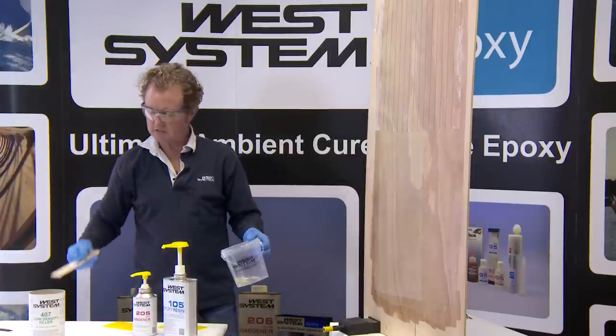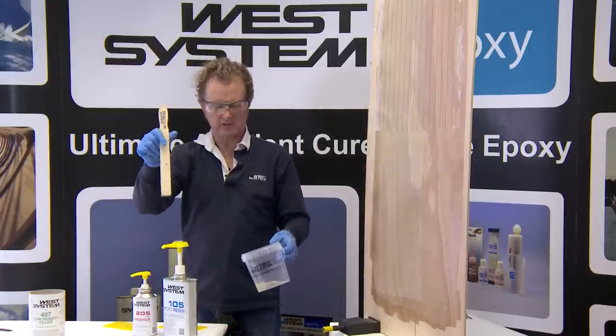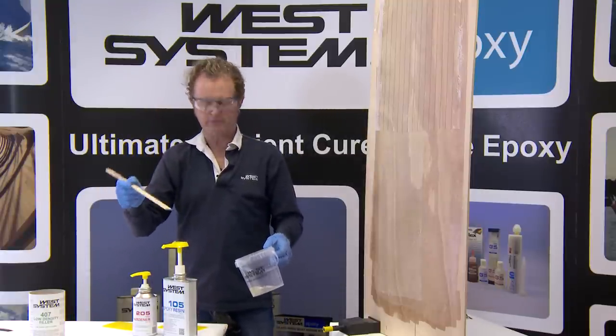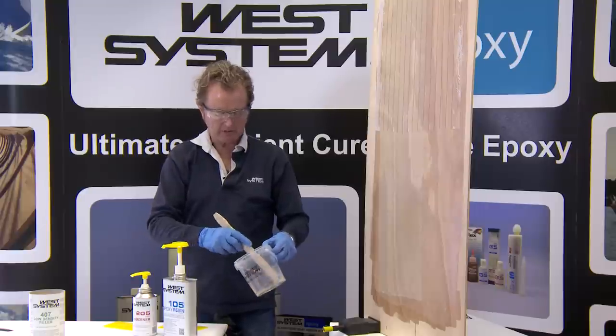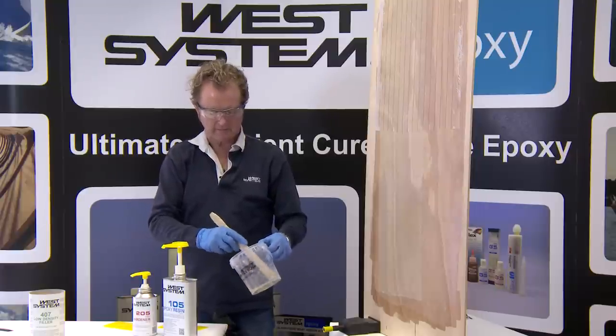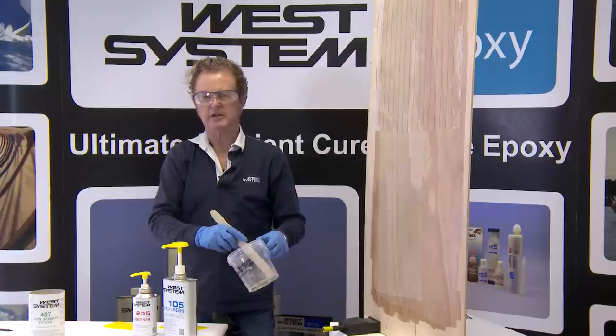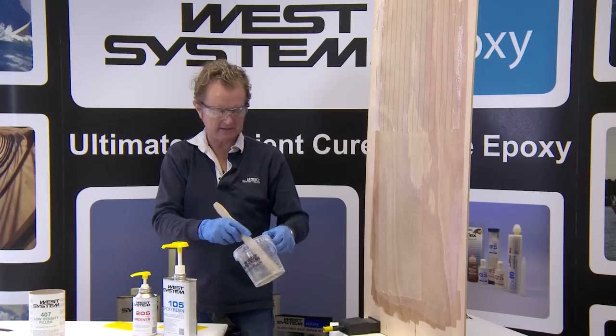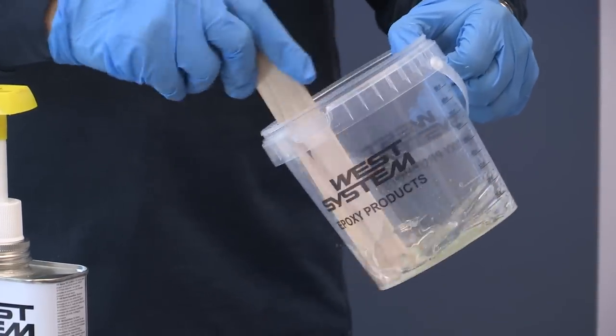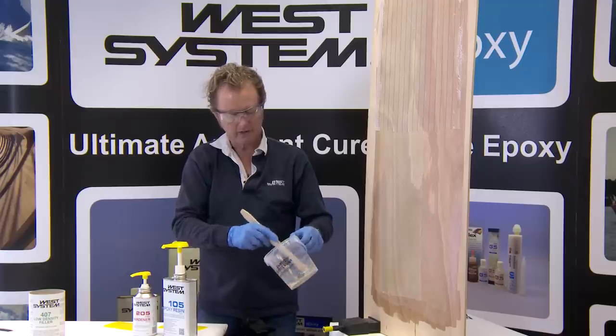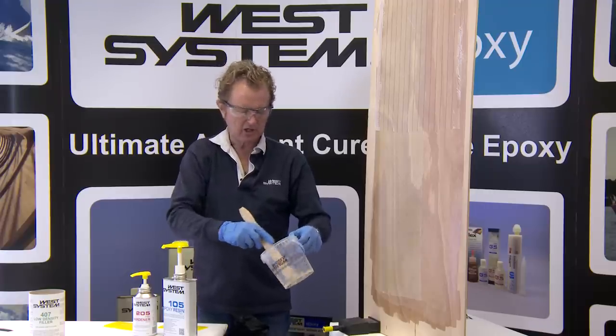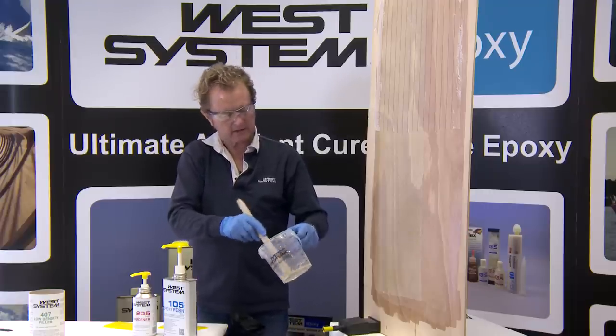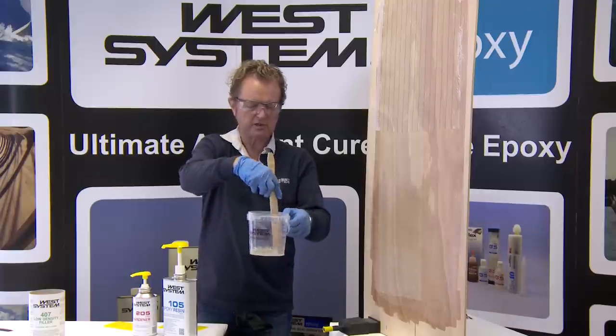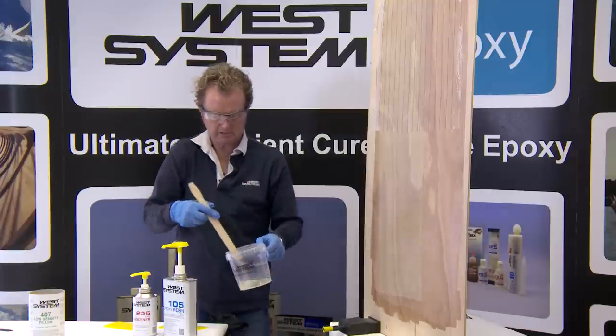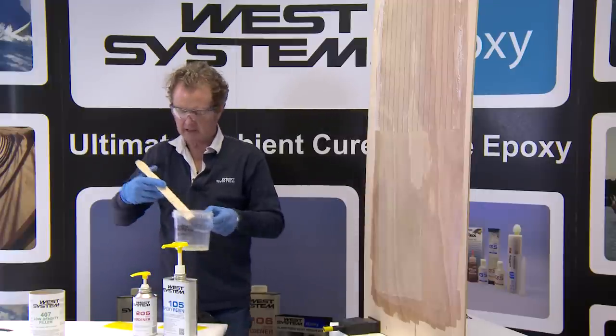And I'm going to blend the two together with this nice hardwood mixing stick. This will help me blend the filler into the mixed epoxy, rather than a smaller mixing stick which tends to bend. I'm going to spend 2 minutes mixing the resin and hardener together. And my resin and hardener mix is a nice homogeneous blend, and I can see that that's true. I've made sure I've mixed around the corners of the mixing pot. Now I'm going to add my low density filler.